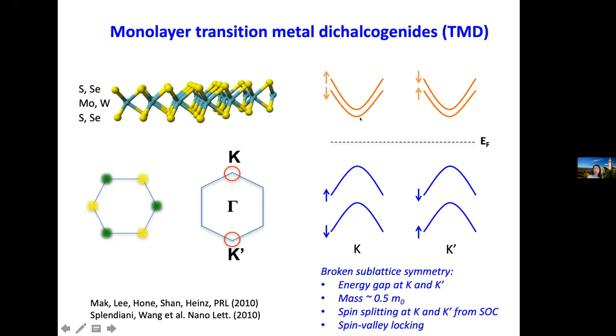The electron hole mass is on the order of half electron mass, as I mentioned before, and the conduction bands are spin split by on the order of 10 meV, and the valence band on the order of 100 meV by very strong spin orbit interaction. And also the spin and the valley degree is locked in this case to obey time reversal symmetry.